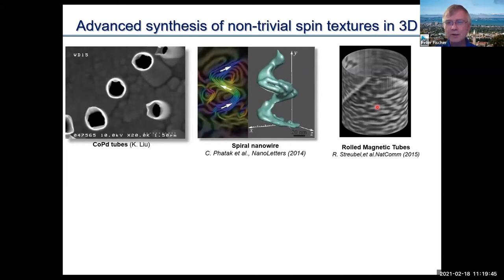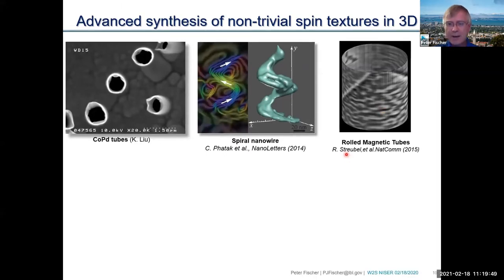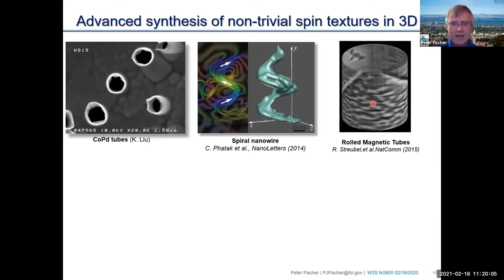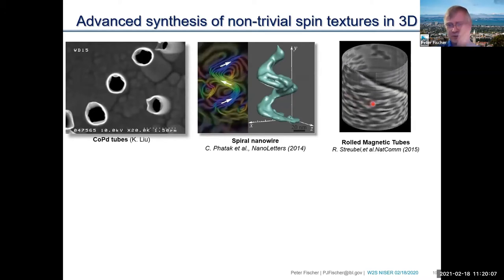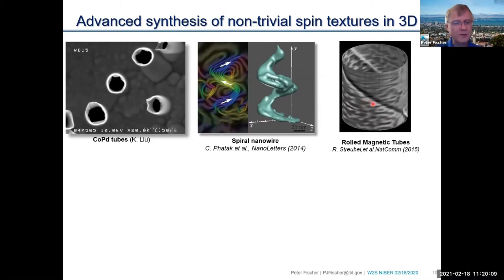And this was work, does it work here? Can we do this again? Anyway, this roll of magnetic tubes also shows you that the spin texture in here changes completely when you put the films that were first flat on a substrate and roll them up like a plastic foil, and the spin texture really changes. Here we go. It's an X-ray tomography image here.